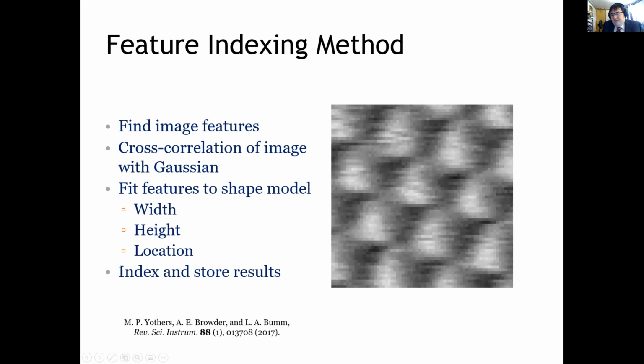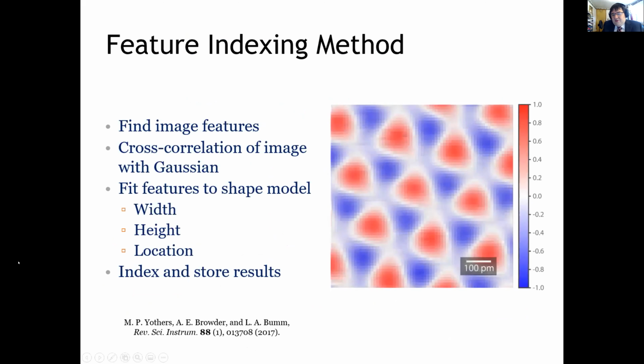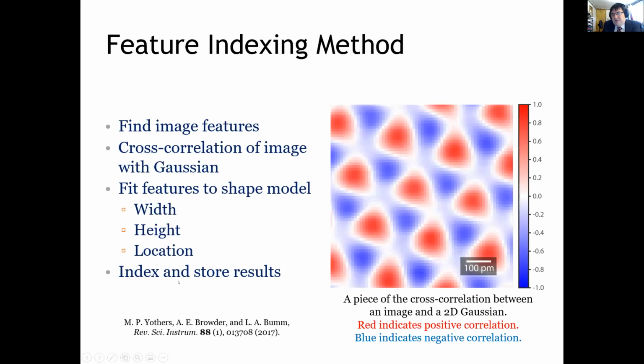We get a grayscale image like this, and using a cross correlation with a Gaussian, we can turn that into positively and negatively correlated areas, which we can use to fit to a shape model that simplifies the data quite a lot. And then index the features so we can look at statistics of individual features later.